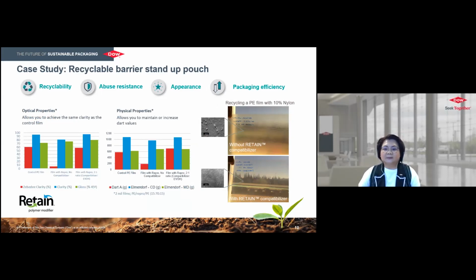Retain was designed as a compatibilizer of polyamide and or EVOH with PE. Without compatibilizer, polyamide or EVOH does not disperse into PE, hence forming big opaque particles. So Retain functions by reacting and forming tiny droplets in the PE matrix as shown in the picture on the right. The left chart shows the film performance comparison of EVOH PE as recycled stream adding into a middle layer of PE film with and without Retain resins. After adding Retain, optical and mechanical properties were significantly improved, even comparable to a PE with 100% virgin resins.